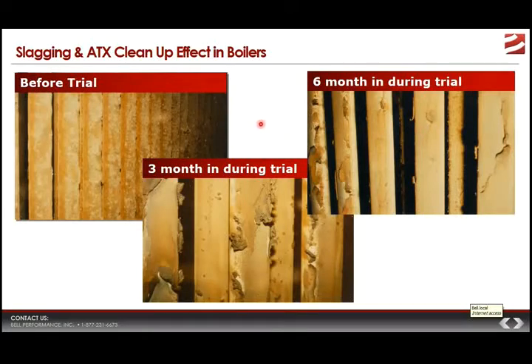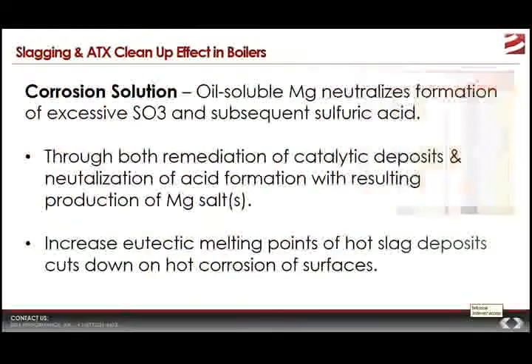So two things that you should be able to take away from this. First of all, the oil-soluble magnesium in the ATX products actually penetrated existing deposits and helped clean them off. Second thing was that it took them between 3 and 6 months, but these kinds of deposits don't build up overnight and they don't get removed overnight, but they will get removed. And you may be able to see the key nuance of this, which is that they did not have to shut down to get this. This happened strictly through treatment of the fuel oil with ATX. It happened over the course of just normal operation. They kept doing the same things they were doing before, and it solved their deposit problems.